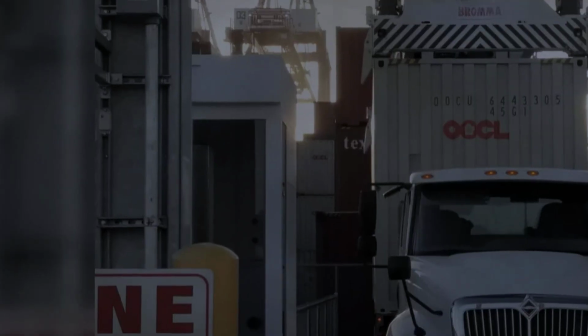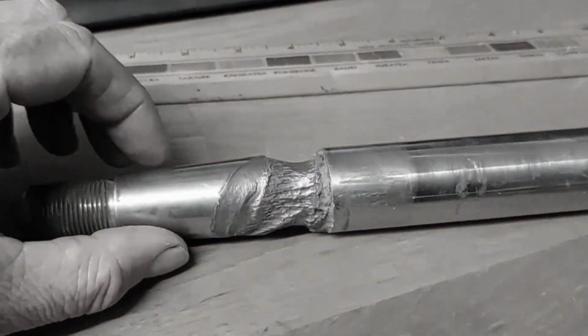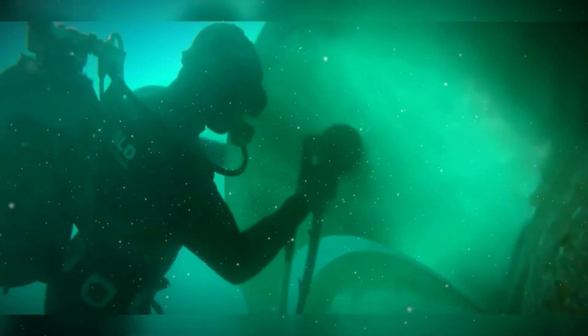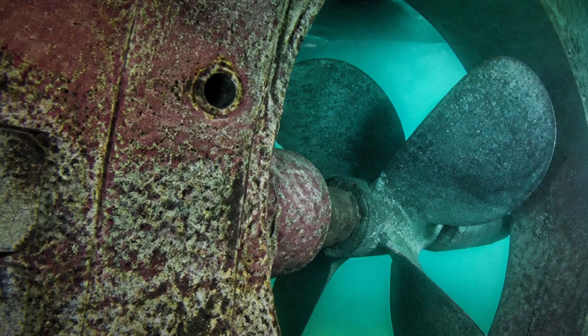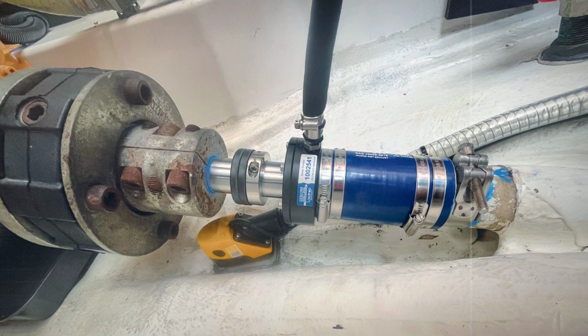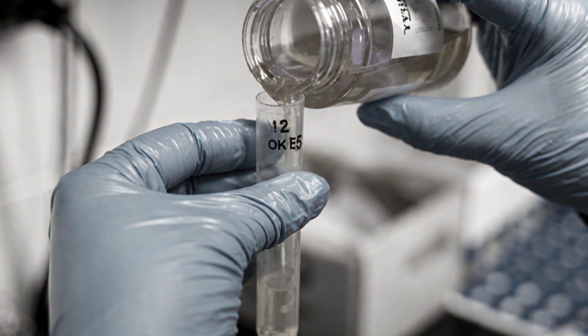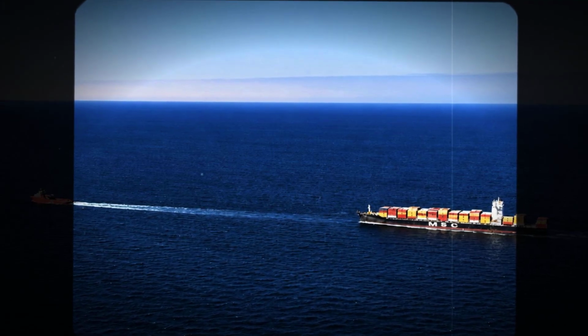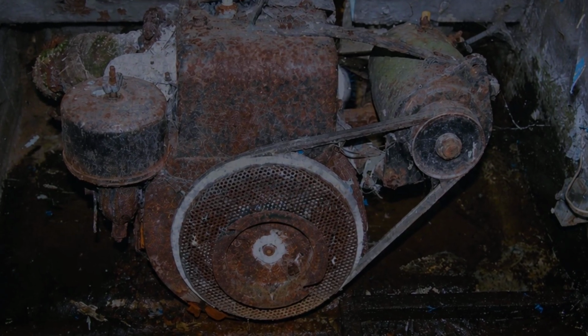But commercial demands can tempt operators to delay these scheduled shipyard visits, and breaking this service rhythm triggers immediate consequences. Without active anodes, the galvanic current begins stripping metal from the next easiest target. Pitting spreads rapidly across the propeller shaft and the surrounding steel hull. This localized decay soon threatens the shaft seal assembly, which keeps seawater out of the ship's internal machinery. If seawater breaches these seals, it corrupts the lubrication system, risking immediate propulsion failure. Neglected maintenance invites mechanical failure.